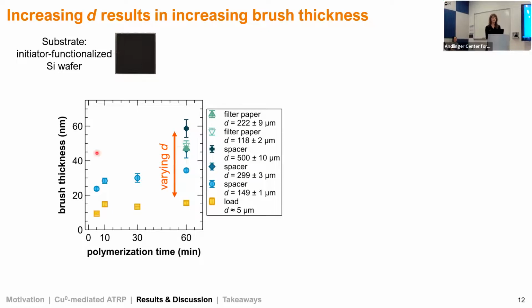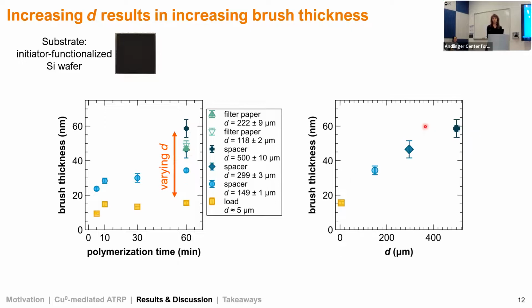So we can also look at brush thickness versus D, which is what I'll show you over here. Starting with the load and spacer methods, all of these thin film methods, we see a pretty strong linear relationship between brush thickness and that distance D. But when we bring in the filter paper methods, we see a higher brush thickness than expected. So this indicates that filter paper, in agreement with what Lee et al. showed for a different monomer, can accelerate brush growth. And that's likely due to reduced concentrations of our deactivator species at the membrane surface.